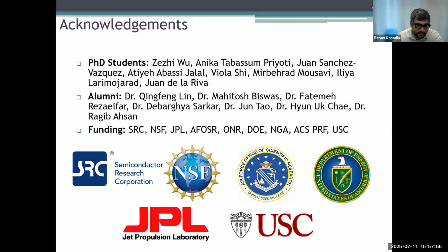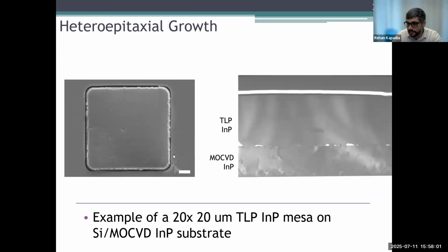And then the last question was, what are these things right at the interface? The really interesting thing here is that I'm pretty sure these are very, very tiny voids at the interface between the MOCVD indium phosphide and the TLP. We've shown that through some other approaches, that there are these small voids that form at the interface.